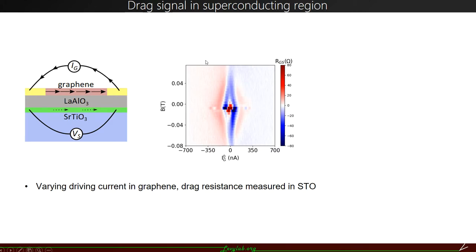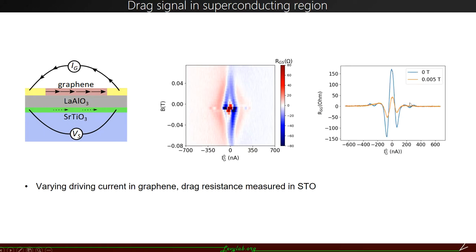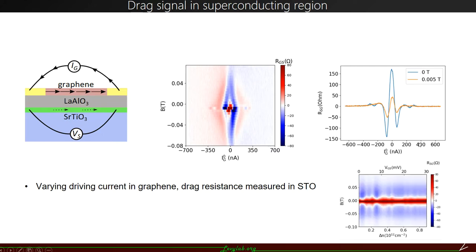Then we measure the drag signal as a function of the driving current. So right here we are changing the current strength in the graphene and measure the drag voltage in SrTiO as a function of the driving current. We can see the signal is greatly enhanced at zero magnetic field, which corresponds to this drag signal enhanced as a function of the carrier density. And if we go outside the superconducting region, the signal is greatly suppressed.